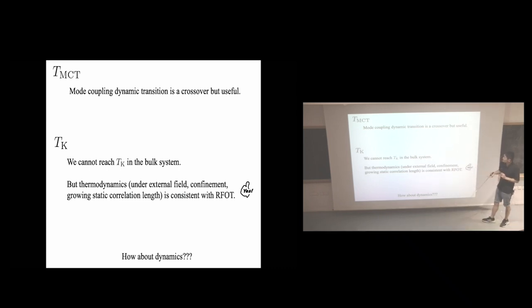I didn't mention this in this seminar, but we can interpret the mode coupling crossover as a sort of vanishing of saddle modes, saddles in a rough energy landscape, et cetera. So it's still useful. For TK, as I emphasized, we cannot reach the ideal glass transition temperature in bulk systems. That's why people call it ideal. But nevertheless, many people, including me, worked hard trying to verify the thermodynamic predictions of random first order transition theory. In particular, we performed extensive simulations with an external field conjugate to the overlap function, and also confinement, which is called random pinning, et cetera. So we have many good numerical data consistent with random first order transition.